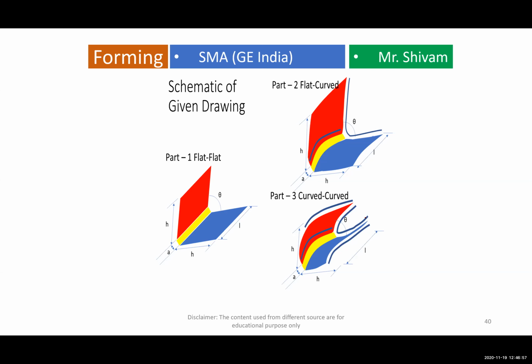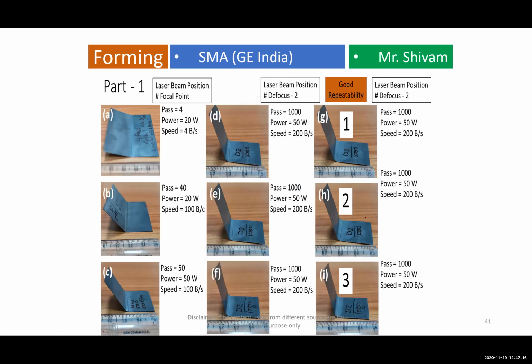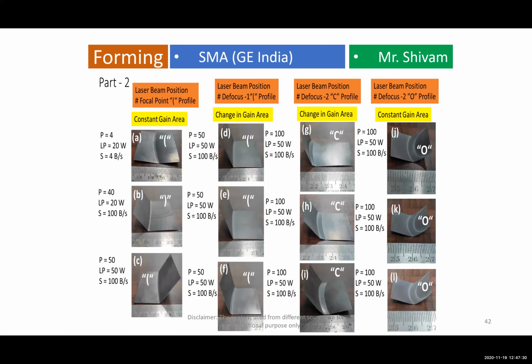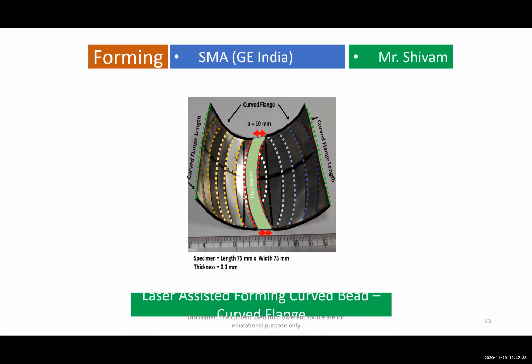So this is one of the collaborative projects with GE India, where they were involved in laser forming of these sheets. These sheets we tried to bend with a die, where some issues were observed. So we went for laser forming, and we wanted to make some kind of corrugated aerofoil structure, which is slightly complex. This corrugated aerofoil structure, we attempted with laser forming with a thin sheet of foil. In fact, we changed the fixture in such a way that we could get the aerofoil. In fact, this is the aerofoil structure which we have made with a flange kind of arrangement. And the interesting part in this is it didn't come back basically. There was a minor deviation, but apart from that, it almost retained its own shape. It retained its shape memory property only to a certain extent, not in a conventional way.